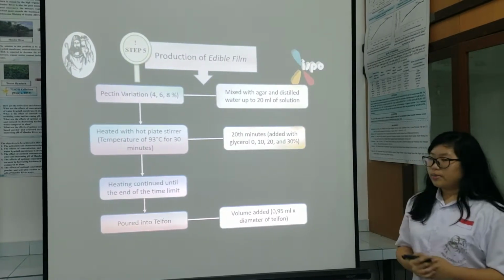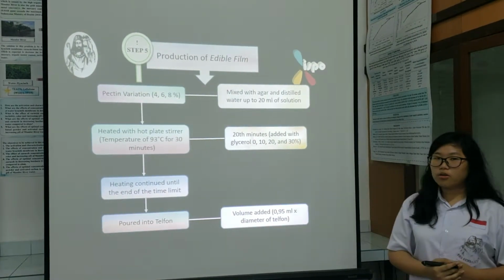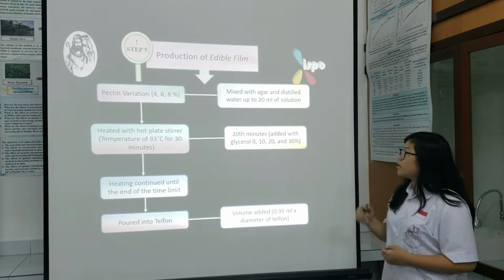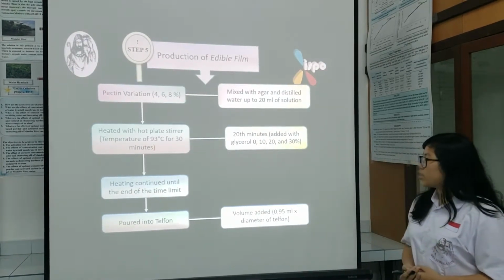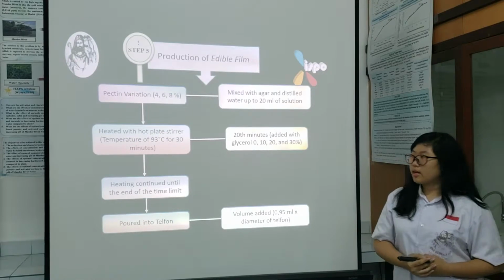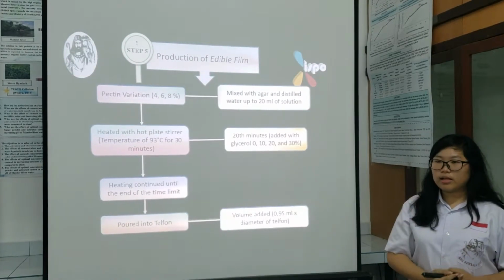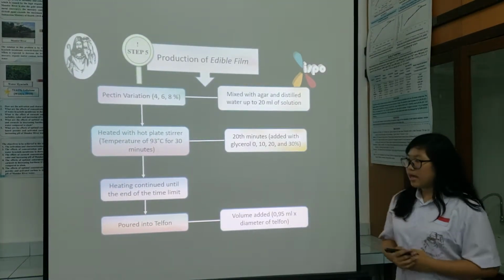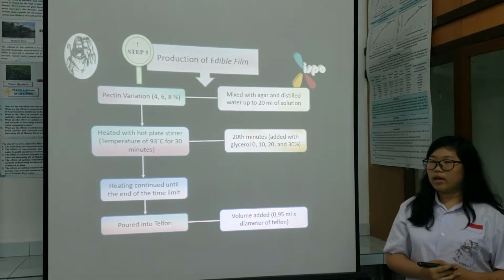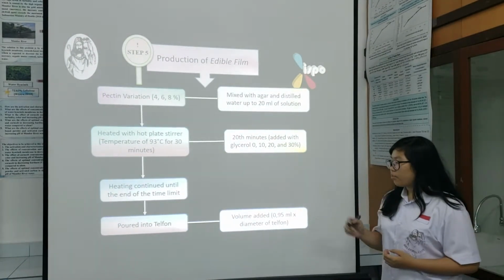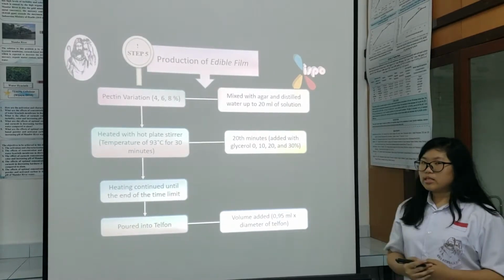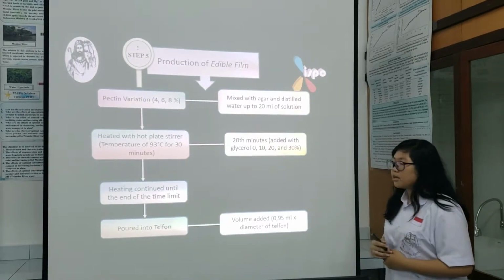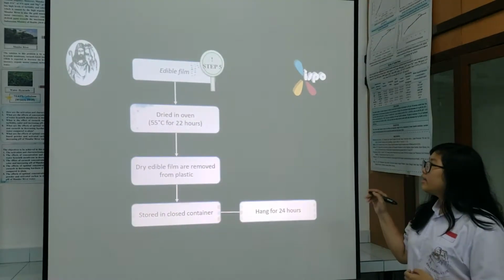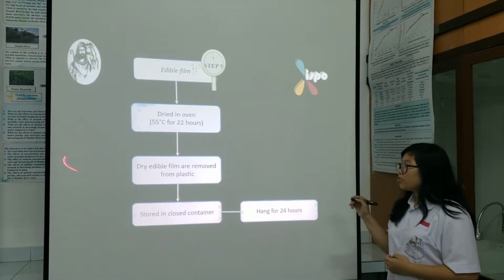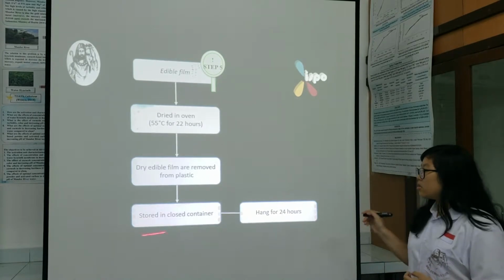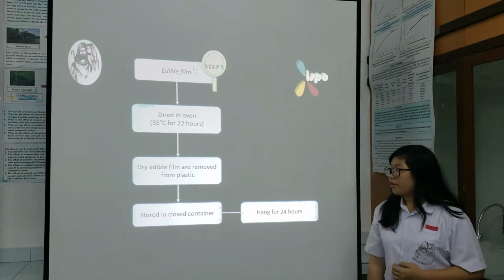Research methodology. There are several steps of research procedures. The production of edible film begins with pectin variations of 4, 6, and 8% mixed with agar and distilled water up to 20 ml of solution. And then it is heated with a hot stirrer, and at the 20 minutes it is added with glycerol with a variation of 0 until 30%. And the heating continues until the end of the time limit. And then it is poured into the Teflon, and the volume which is added is equal to 0.95 ml times the diameter of Teflon. Then the edible film is dried in the oven, and the dry edible film will be removed from the plastic, stored in a closed container, and hung for 24 hours.